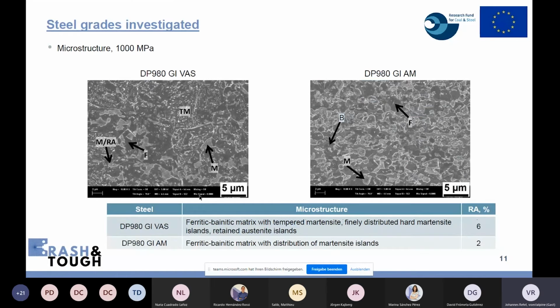On the left-hand side, you can see the dual phase grade, strength 1000 megapascal, which had some retained austenite. This is a more complex microstructure with ferritic bainitic matrix, some tempered martensite, and finely distributed hard martensite islands and some retained austenite. And on the right-hand side, you can see the DP980 GI AM grade with negligible content of retained austenite. This grade has a ferritic bainitic matrix with distributions of martensite islands.